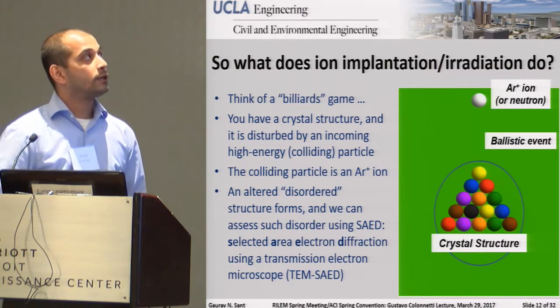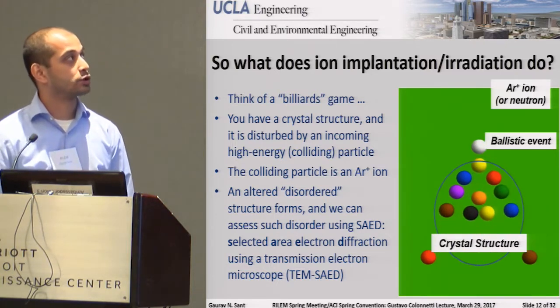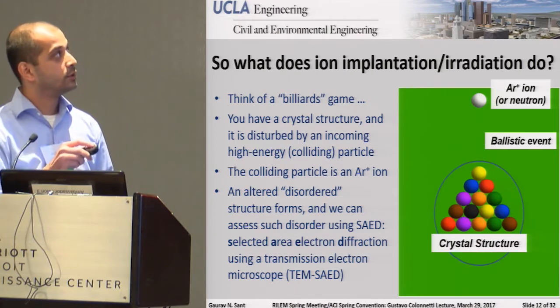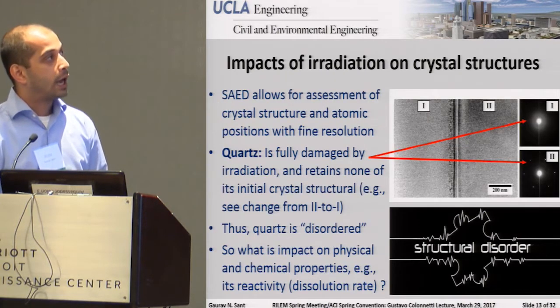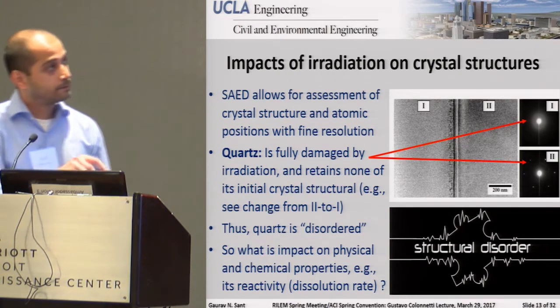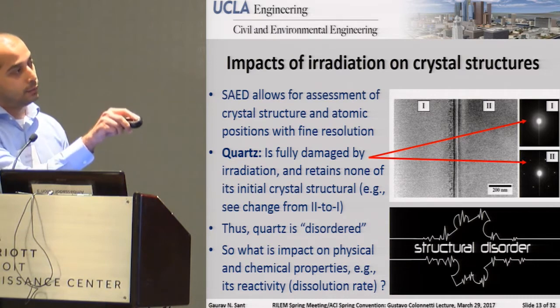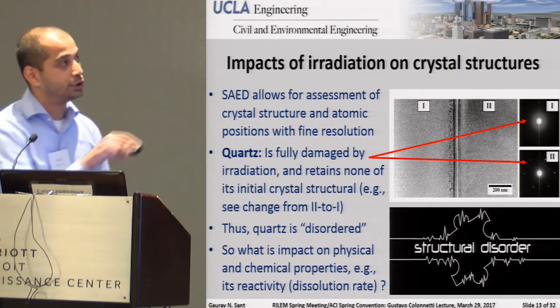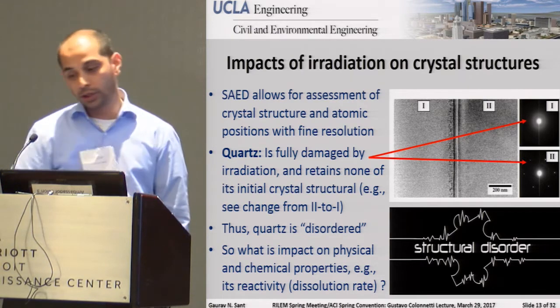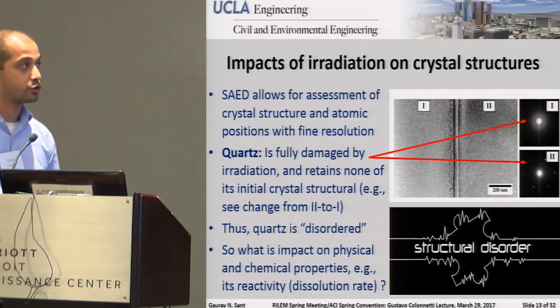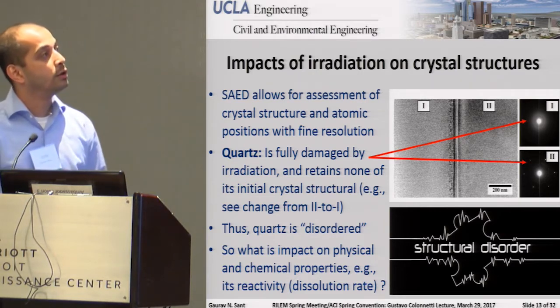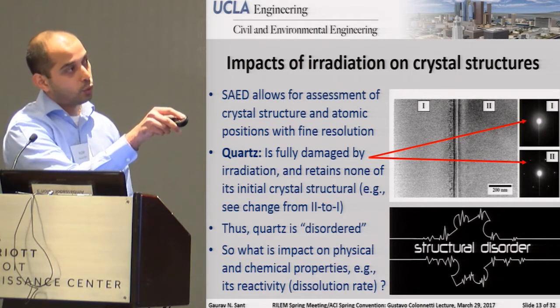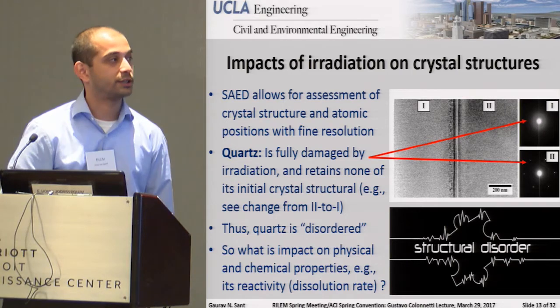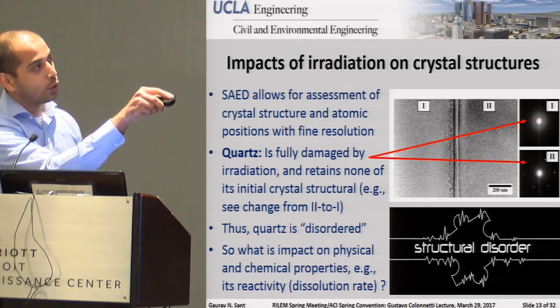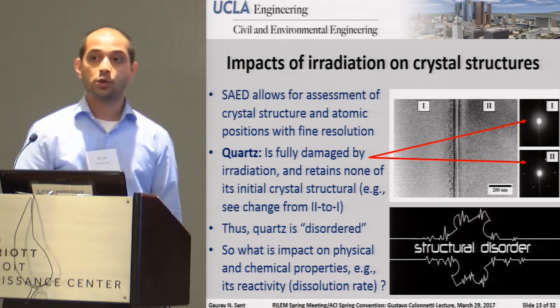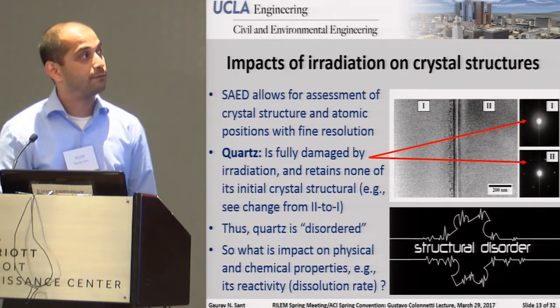Now, to look at the idea of irradiation a bit more scientifically, of course, you can do what's known as selected area electron diffraction. And what I want you to consider is really two things. So I want you to look at these two images right here, what those images really show. The first one shows quartz under a transmission electron microscope, specifically in SAD mode, where you can get what is known as the sharp diffraction maxima, and you can see these six ordered spots right around it. So this is quartz like it originally was in the pristine form.